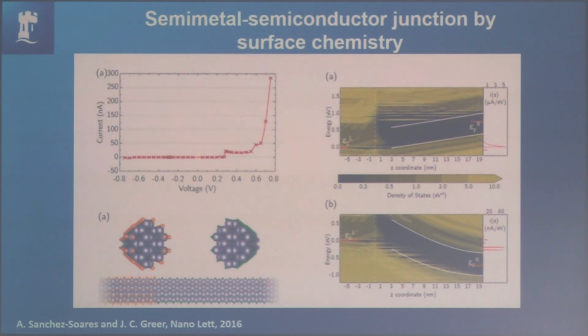But if I try to go the other way around, I can't get charges through there. What you see sticking out here are evanescent states from the metal surface in the band gap. These are states, but they're not enough to actually turn the device on. So you get a nice rectification simply by changing the surface chemistry on a thin film. So again, if I can make a diode, and if I can make two back-to-back diodes, and if I can put a gate on it, I can make a transistor. So this is where we're looking at the moment. Can we actually do this? Would it be easier with this material and using these ideas rather than fighting the bismuth states? We don't know. So it's work in progress.